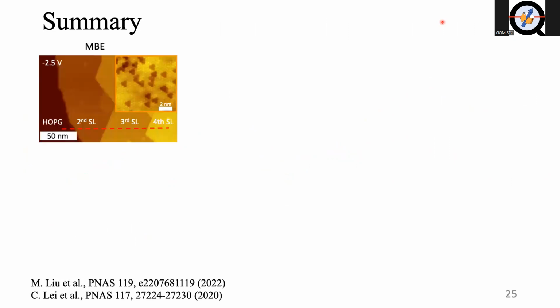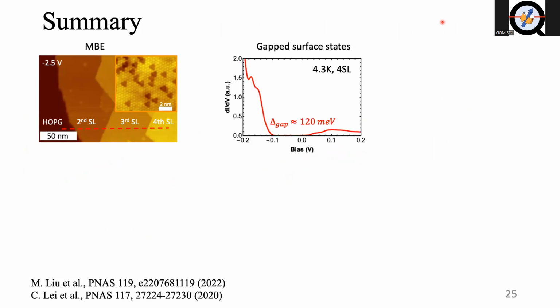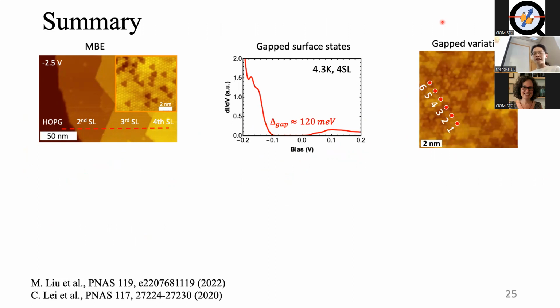First of all, we use molecular beam epitaxy to grow thin films of MBT layer by layer, in a very intrinsic, low defect condition, which allows us to observe gapped surface states. In the fourth septuple layer case, we observe a 120 meV exchange gap. And we also observe that the Dirac mass gap can vary as a function of local defect density, and it can collapse in high defect regions.